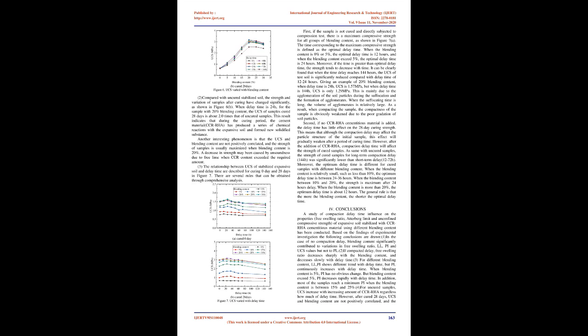Another interesting phenomenon is that the UCS and blending content are not positively correlated, and the strength of samples is usually maximized when blending content is 20%. A decrease in strength may have been caused by unsoundness due to free lime when CCR content exceeded the required amount. 3. The relationship between UCS of stabilized expansive soil and delay time is described for curing 0 day and 28 days in figure 7.